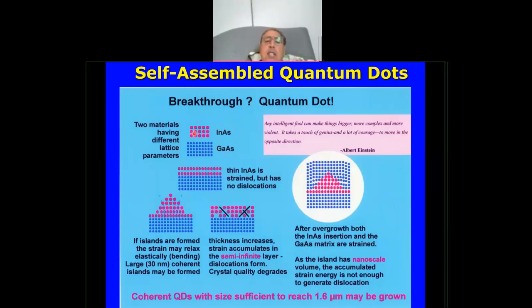And because these two semiconductors have a different lattice constant, that means the size of the lattice is different. When you try to deposit a larger lattice on top of a smaller lattice, what is happening? You're going to have some strain, and when you go above a certain thickness, that strain becomes like an island. It creates this island.